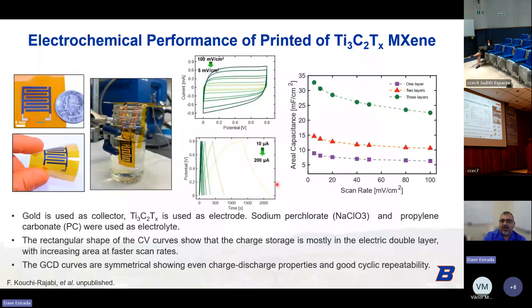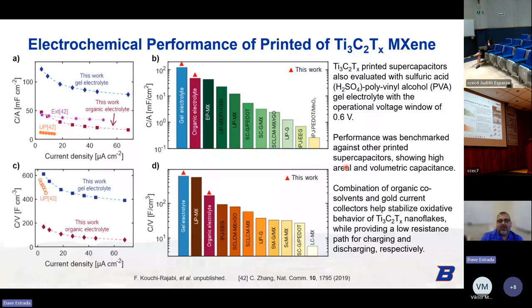And then we can integrate these curves to get the areal capacitance, divided by the total area of the electrodes. And we can see that scales well with the number of passes. We stopped at three passes because if we add more MXenes, they start to delaminate off the surface. So we benchmarked this against the literature, and we can see here the areal capacitance for the organic electrolyte, and then the gel electrolyte is outperforming some of the best printed MXene electrochemical devices in the literature.